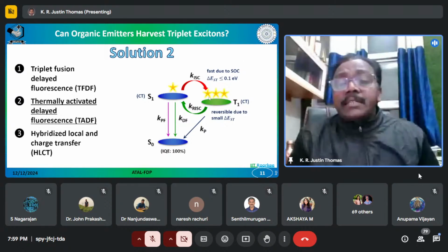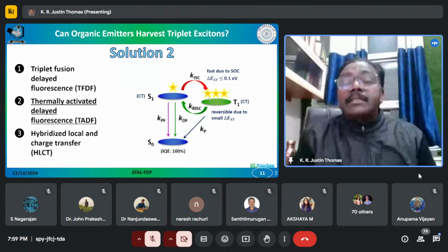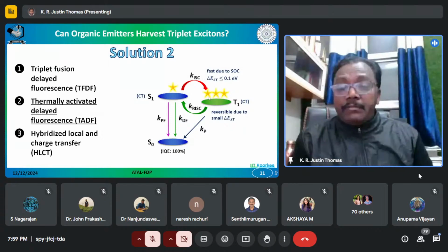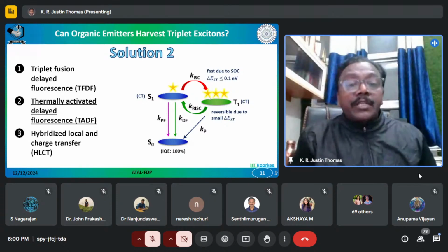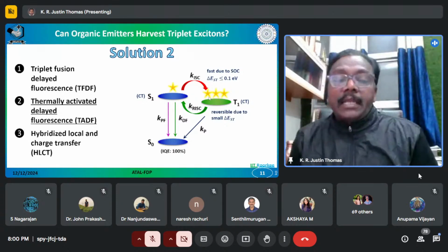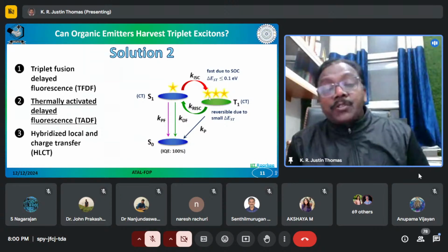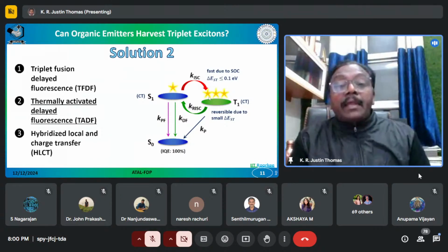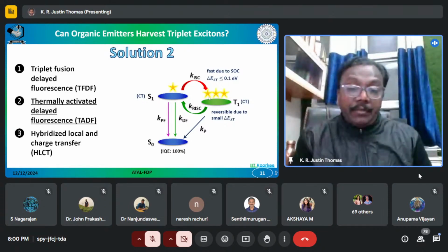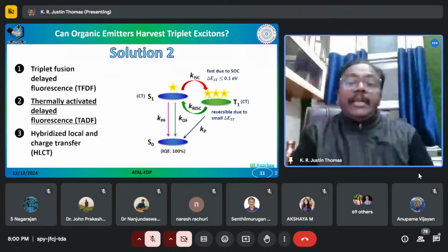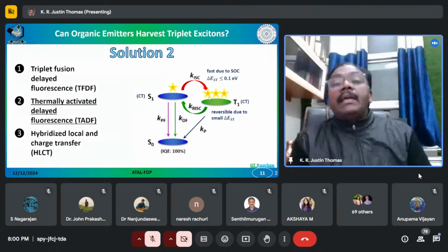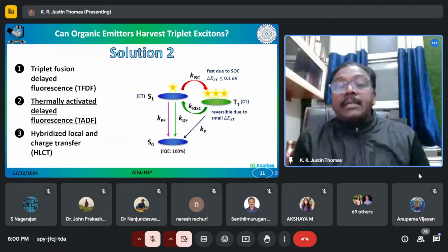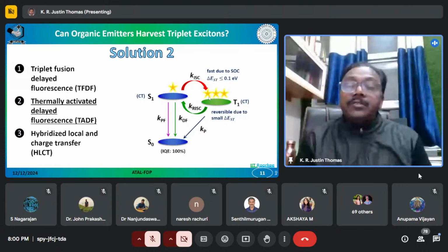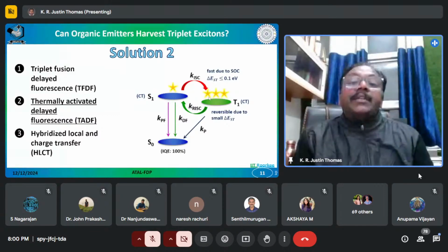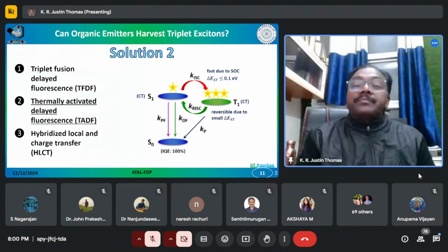So one of the characteristics of TADF materials is that they will have two fluorescence lifetimes. One will be in the nanosecond region, that is the typical fluorescence lifetime, and another will be in the microsecond region, which is typically a phosphorescence lifetime. In some cases, if the inter-system crossing is so fast, you will have a much shorter lifetime, but it will not be in the nanosecond region. It will always be in the microsecond region.